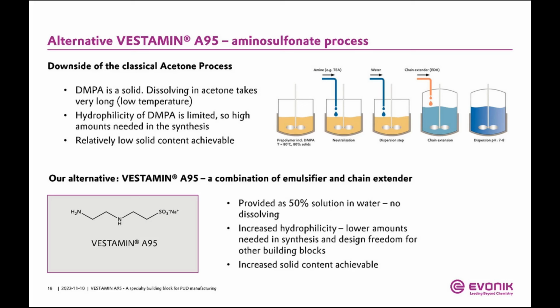Okay, our next question. How much VESTAMIN A95 should be used? That's a good question. As I showed in the tables, in order to achieve the highest solid content, you should put as much A95 in your formulation as possible. As much as possible means in this case just a stoichiometric amount. In our cases, we always use exactly 1-to-1 stoichiometry of NCO to amine. The amine in this case is the A95, the chain extender, and you want to choose exactly a 1-to-1 stoichiometric ratio to the amount of NCO you have in your prepolymer. This is the case if you go for the highest solid content.